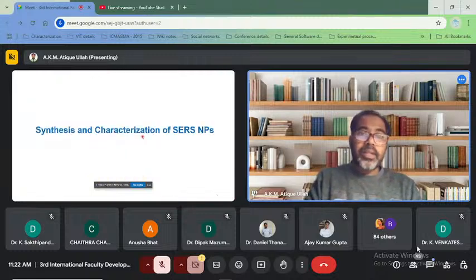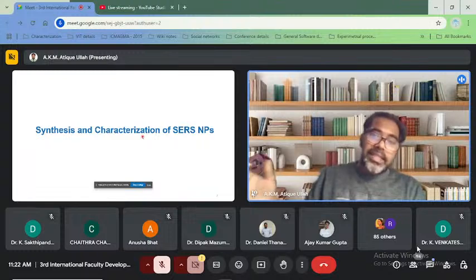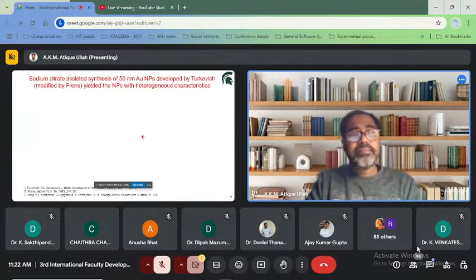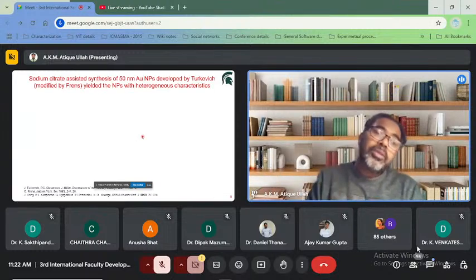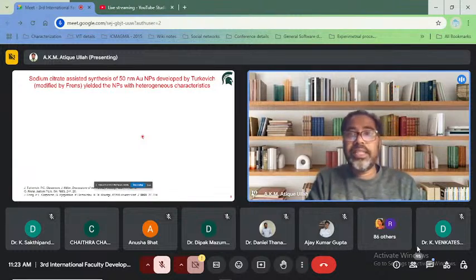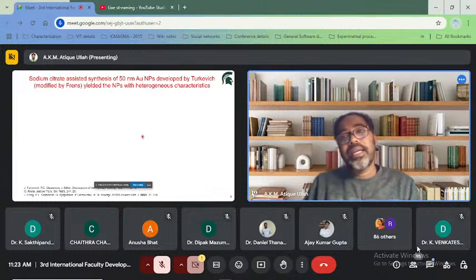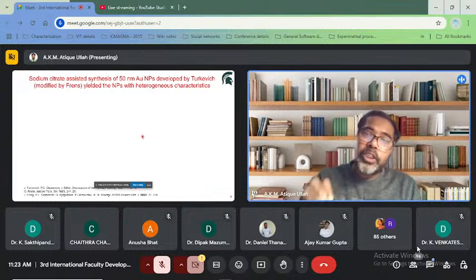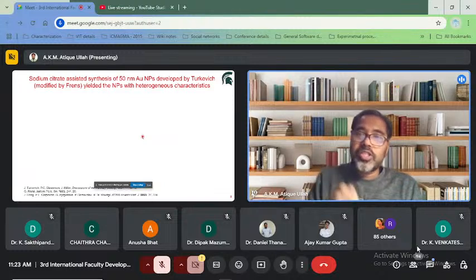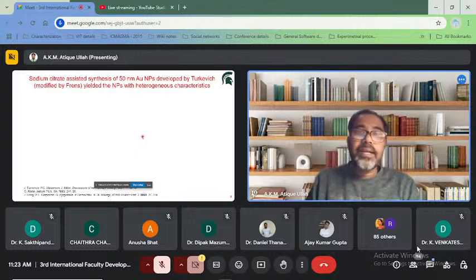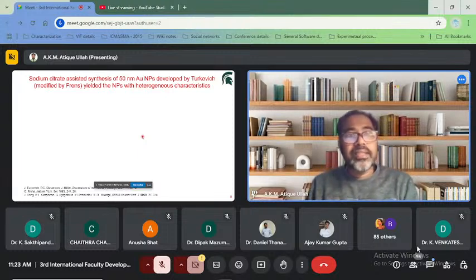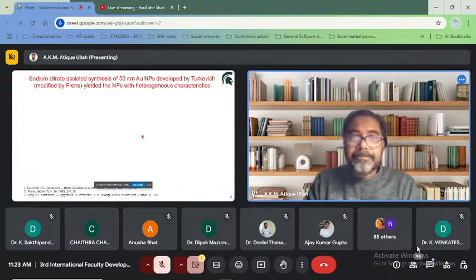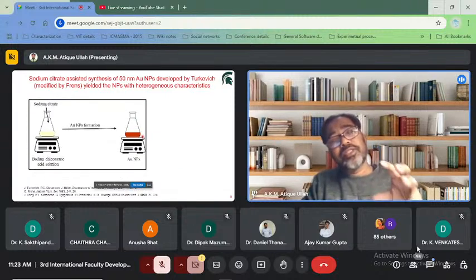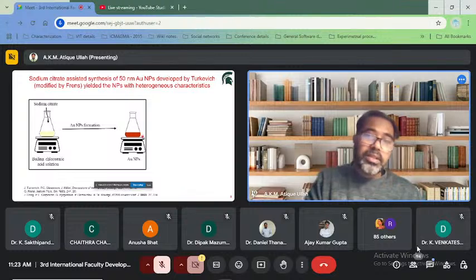So then, moving to the synthesis and characterization of the SERS nanoparticles. The most common method used for the synthesis is called the Turkevich method. In the Turkevich method, usually the gold salt, for example chloroauric acid, is the precursor, and sodium citrate is the reducing agent. This is the most common method to synthesize gold nanoparticles.